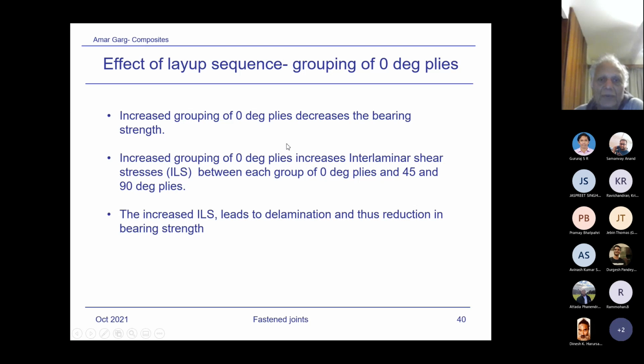Okay, so I just wrote in summary: increased grouping of 0-degree plies decreases the bearing strength. Increased grouping of 0-degree plies increases interlaminar shear stress between each group of 0-degree plies and 45 plies, and the increased ILS, interlaminar shear, leads to delamination and thus reduction in bearing strength. So what happens with these layup sequences? They do affect the free edge stresses, which would be taught to you if you are attending some laminate design courses to explain what is interlaminar stress. In fact, that's one of my favorite topics. If there's time later on, I might discuss the laminate design and guidance from the interlaminar stress point of view.